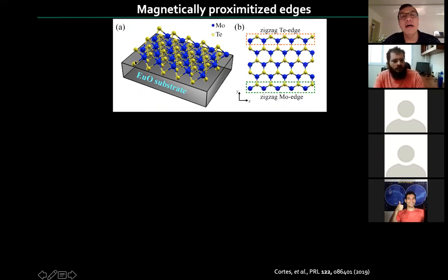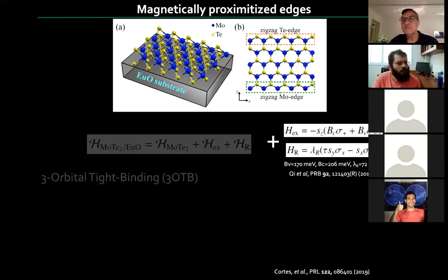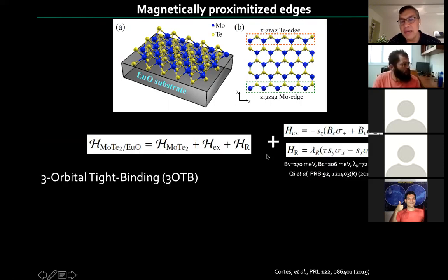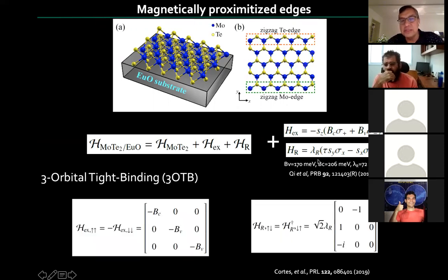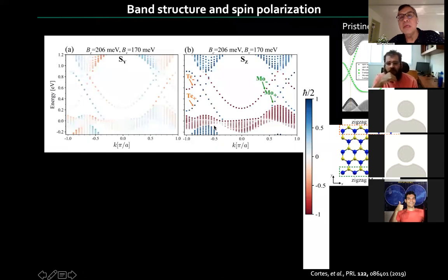I have a magnetic substrate with this molybdenum telluride in this case, for commensurability reasons. And just like we had the tight binding Hamiltonian, you can include magnetic exchange and you can include a Rashba field to make it more in accordance with this. This is a bit technical, let me skip that. This is the result. So remember, I have the different gaps. The bulk gaps are different on the two valleys, like I indicated in the other slide. There are the edge states that are now split, because it's like I'm applying again a magnetic field right on these edges. So the two different spins have now split, and I end up with levels that open up like that.